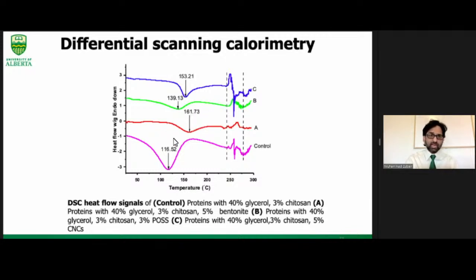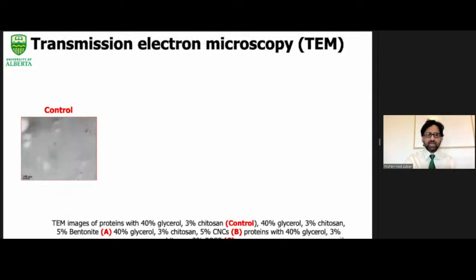And we can see that the A, the bentonite nanoparticle containing film, has the loss increased up to 161.73. That shows that the maximum interaction has been developed in case of bentonite with the films. Furthermore, transmission electron microscopy was performed to see the internal structure changes after the addition of the nanoparticles.